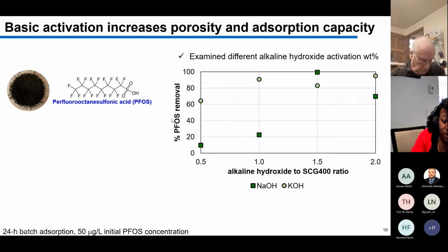So what we did was, again, we plotted percent PFOS removal this time on the y-axis, still 50 microgram per liter, still a 24-hour batch adsorption test. And here we tested two different chemical activating agents that were added in during the second pyrolysis step. So the dark green squares here indicate where we added a certain mass of sodium hydroxide versus the lighter green circles where we added potassium hydroxide. These are both caustic materials, so we wanted to achieve this activation and increase in surface area without having to rely on too much of this caustic material, because again, we want to make sure this process is going to be environmentally benign and not result in a lot of extra contamination.